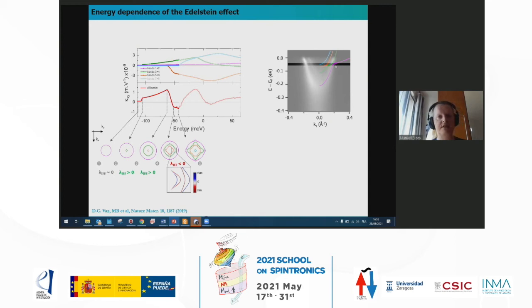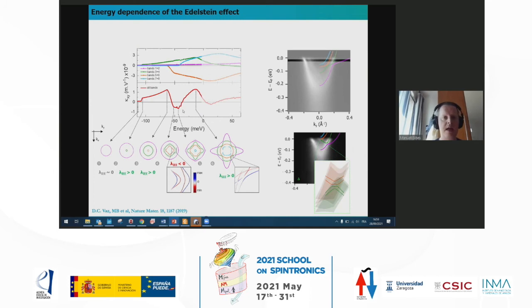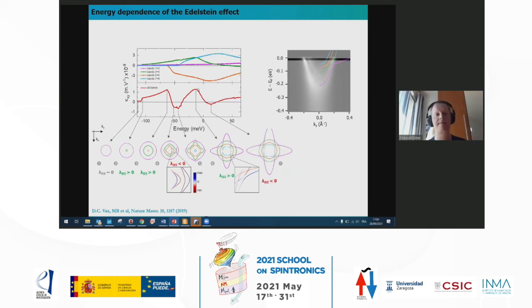And then we enter this interesting regime where we have a strong interaction between the bands and the maximum Rashba splitting. And you can see here the colors, blue and red, correspond to the direction of the spin pointing, let's say, up or down. Okay, so this is maximum Rashba splitting, and we have here a negative maximum in the conversion. Eventually, we increase further. We reach this peculiar point that I described before, where this is this topological level crossing. We also have a maximum, and then we have another maximum and minimum.